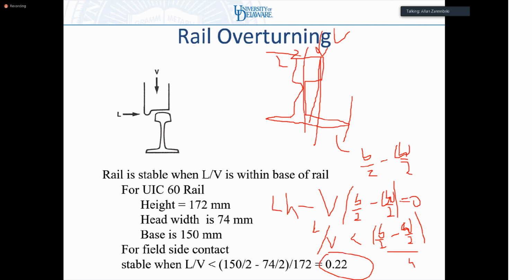So you notice that if I have contact on the field side of the railhead, which I do get with worn wheels, then my overturning stability is actually less, and I have a greater risk of overturning. I also see this on the low side of curves, where I will have my contact on the field side, and I have the potential of overturning my rail on the low side of a curve as well.